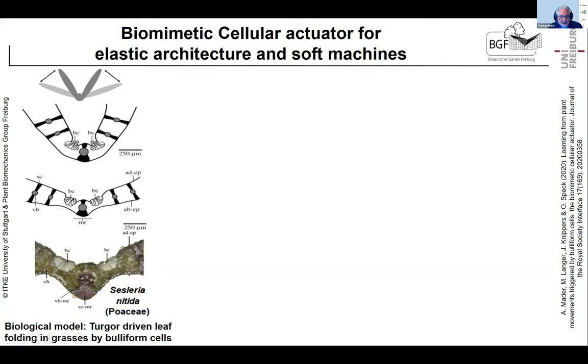And each bulliform cell, which you see here, has stiffened walls at the sides and at the base, here, here, and here, but the top wall is not stiffened. And if you inflate them by the internal turgor pressure of the cells, which is around 1 to 2 bars, then they inflate and open on top, because the top layer is flexible where the side layers and base layers are stiff. By this opening, they put pressure on the side, so the leaves open if there is turgor in these bulliform cells, and they close if there is reduced turgor in these cells.